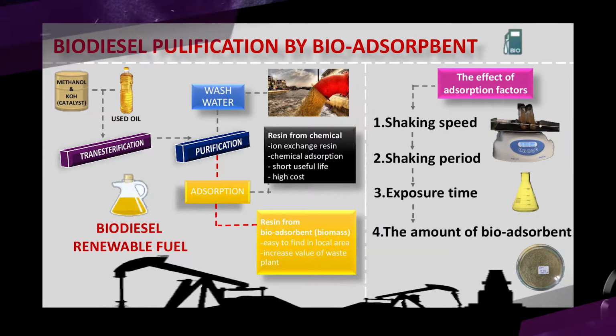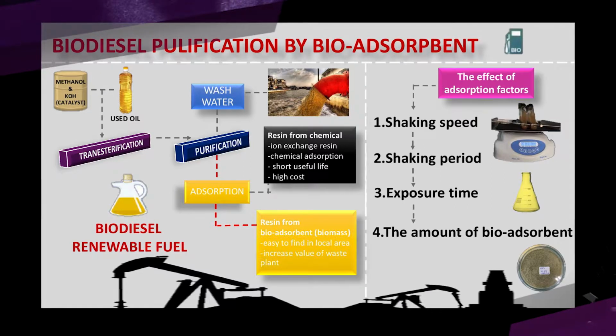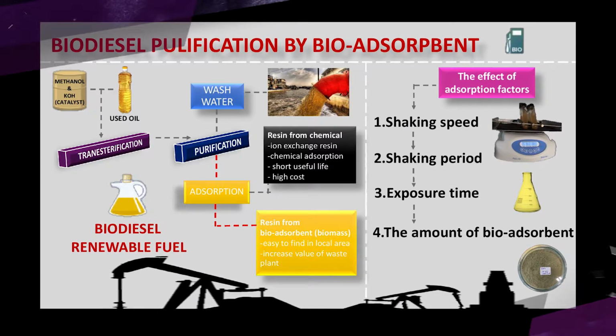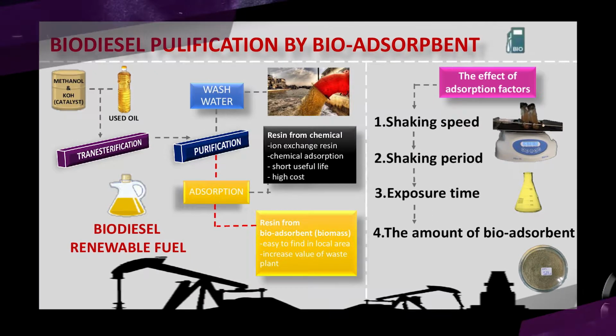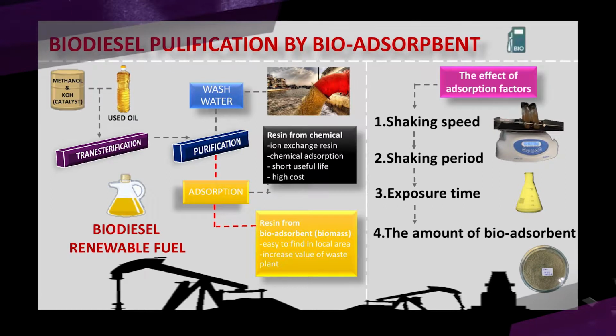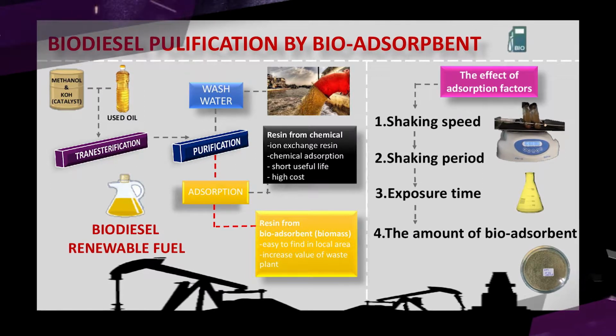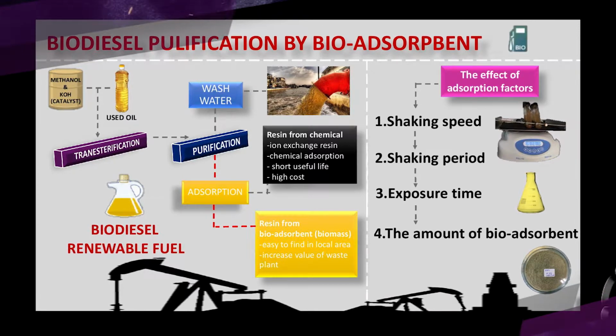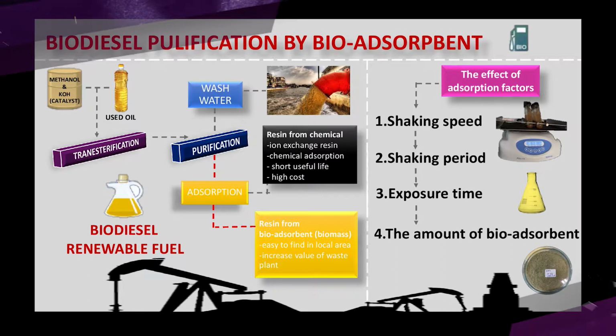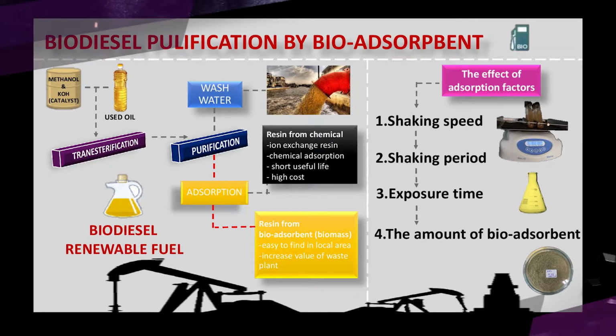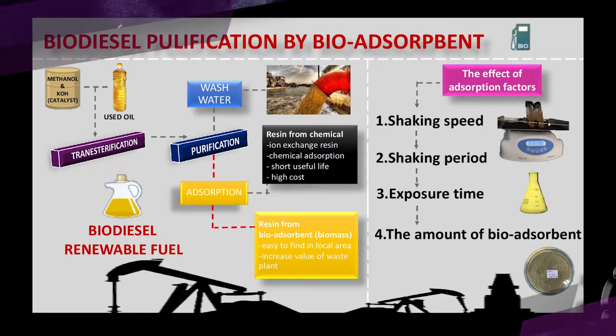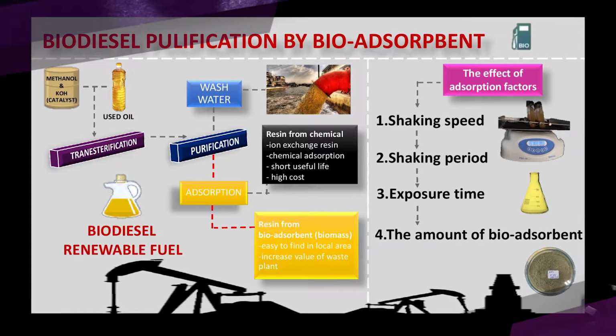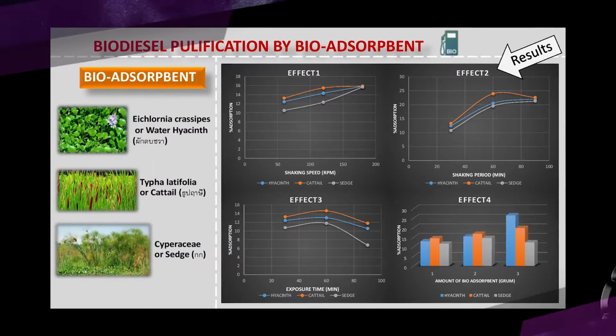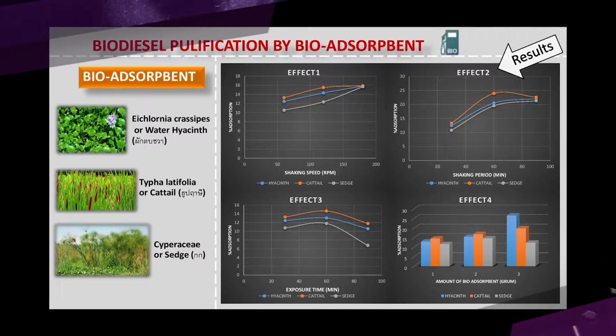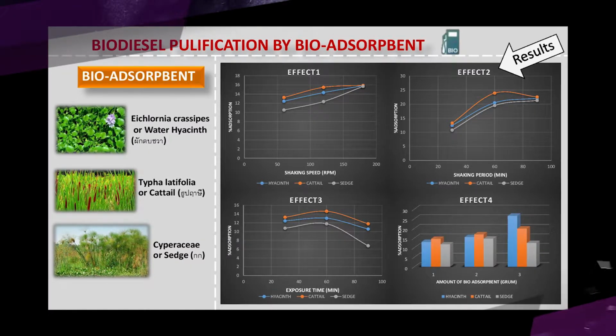Bioadsorbents were prepared from different plants for adsorption of potassium ion in biodiesel, and the potassium ion value was tested by conductivity meter. The adsorption performance of the bioadsorbent was evaluated from potassium ion in biodiesel at different adsorption conditions such as shaking speed, shaking period, exposure time, and the amount of bioadsorbent. We make the bioadsorbent from different types of plants, which were water hyacinth, cattail, and sedge. From the experiment, we get the percentage of potassium adsorption by bioadsorbent.